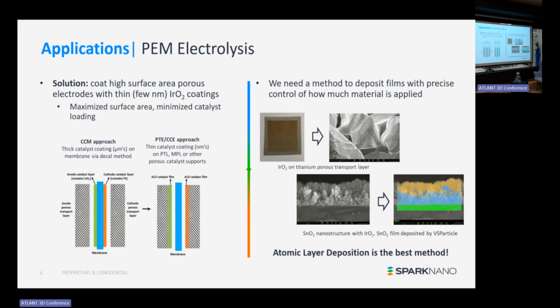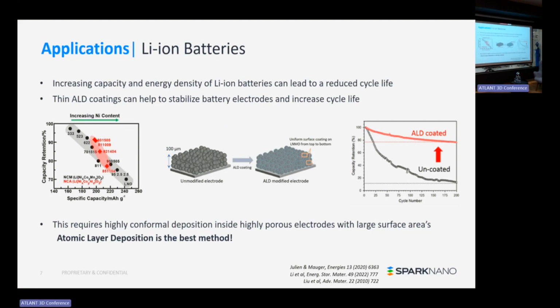There are some examples of iridium oxide processes we did on the titanium porous transport layer, where every individual titanium fiber is coated with a 5 nanometer film of iridium oxide. We also do these things in nanoporous structures. This is nanoporous tin oxide, and this is EDX mapping. Green is silicon, blue is tin, and orange is iridium. So we can have nice halfway penetration depth control of the iridium oxide film. Of course, for depositing thin films with a high amount of control into porous substrates, ALD is one of the best methods to do that. Another application we're working on is lithium-ion batteries.